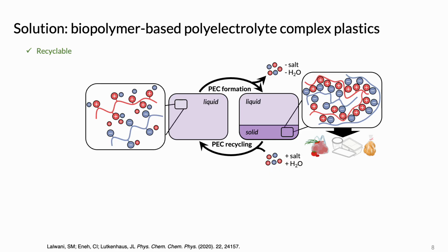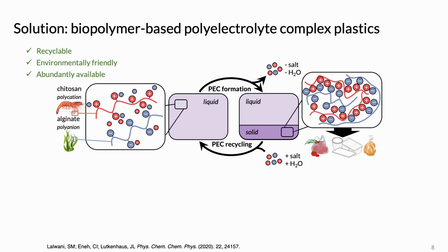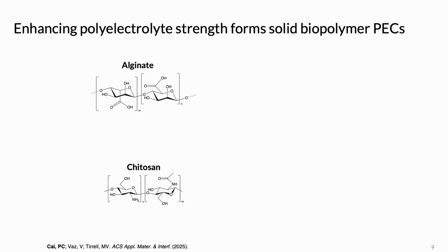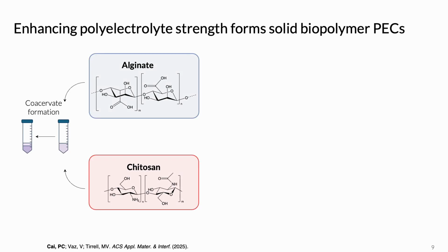Secondly, we want the material to be environmentally friendly and not rely on petrochemicals. So I decided to use biopolymers as the polyelectrolytes because they're naturally derived and possess inherent biodegradability. I chose chitosan, which is derived from crustacean shells and fungi, and alginate, which is derived from seaweed. So first, I tried mixing alginate and chitosan together, thinking that their charge groups would help me form the solid polyelectrolyte complex seen in other polyelectrolyte systems.